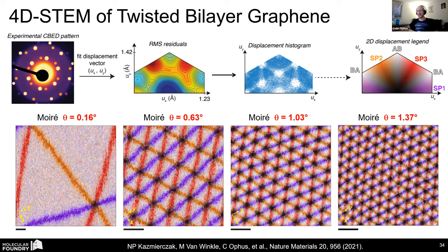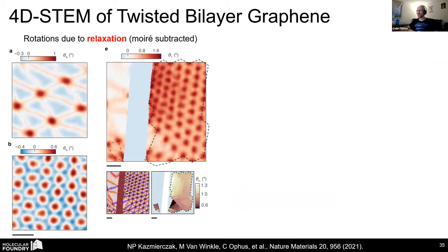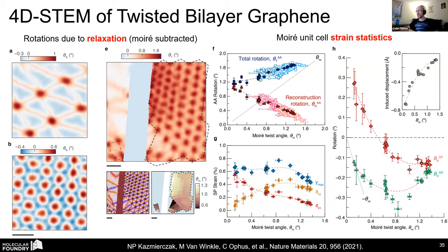Displacement, of course, is just the integral of strain. So if you can smooth these images a little bit and differentiate them, then you're able to get the local strain tensor. And this is the infinitesimal rotation tensor after subtracting the Moiré rotation. What we did is measure the deformation unit cell by unit cell to get a lot of statistics here of the local Moiré cell deformation.